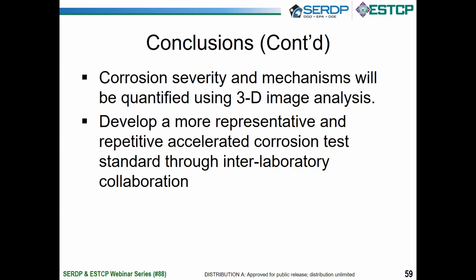We also plan to assess corrosion severity and type of corrosion using 3D image analysis, optical profilometry. This will allow us to have a better quantifiable way to assess the type and extent of corrosion. Overall, our plan is to develop a more representative and reliable accelerated corrosion test standard through inter-laboratory collaboration. Again, we're doing this through round-robin testing to address the issue with current accelerated corrosion tests in their variability, both between labs and between tests.